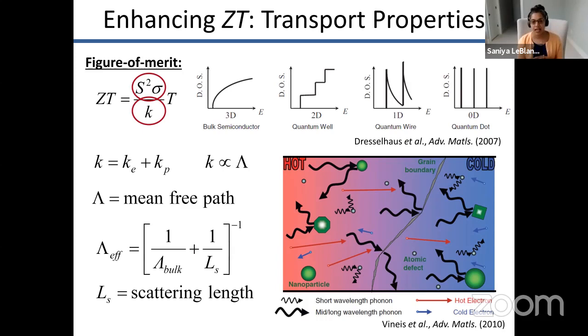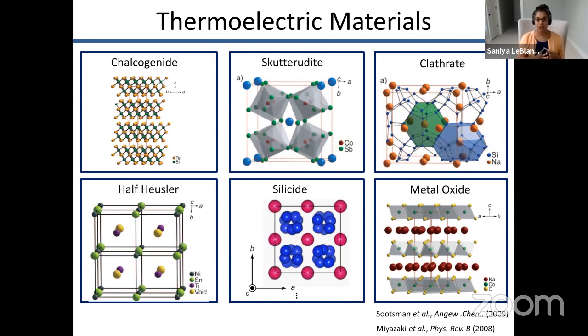And so if we introduce features into the material that can impact how the phonons go through the material, if they act as barriers that the phonons can bounce off of, that changes the mean free path. So it changes how far this phonon can go before it scatters and has to go in another direction. And that means that it can actually reduce the thermal conductivity. So these are the ways that we think about how we can actually change thermoelectric materials. So on this slide, I'm going to show some structures. These are diagrams that show you where the atoms are. So unit cell diagrams show you where the atoms are in different kinds of thermoelectric materials.